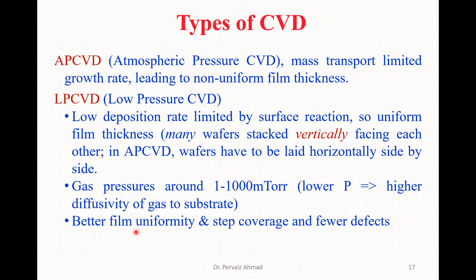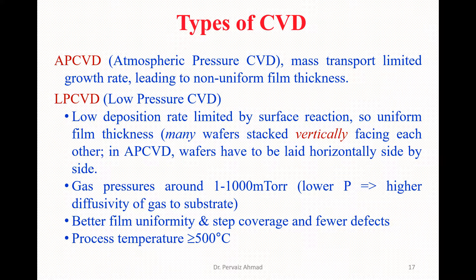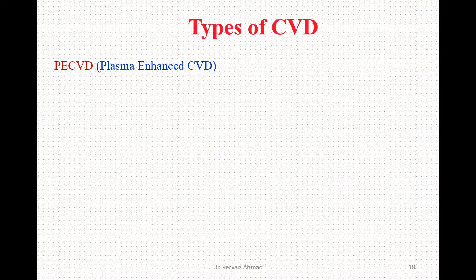LPCVD gives excellent film uniformity, step coverage, and fewer defects. Since the deposition process is at low pressure, we have very few defects in the synthesized thin film. The process temperature is equal to or greater than 500 degrees centigrade, which is comparatively lower than what we use for boron nitride thin film synthesis, which goes beyond 1200 degrees centigrade.